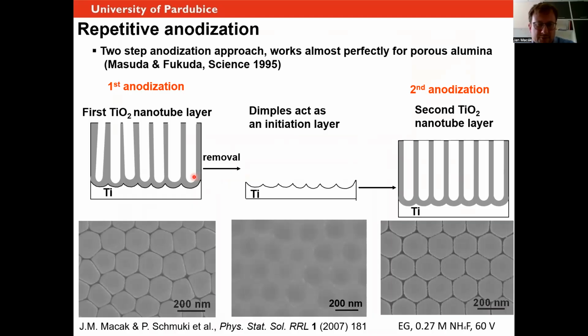So I'm sorry that I'm sometimes showing you some rather older papers, but for the story, I'd like to say it and also remind it. So in the alumina case, there are significant papers showing that if you do something like, for instance, repetitive anodization, you can improve the ordering. And it works really almost perfectly for porous alumina.